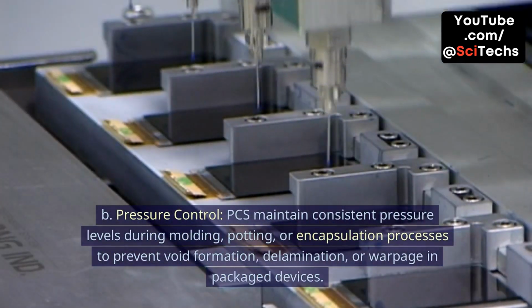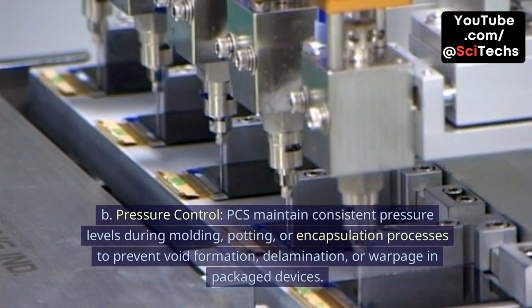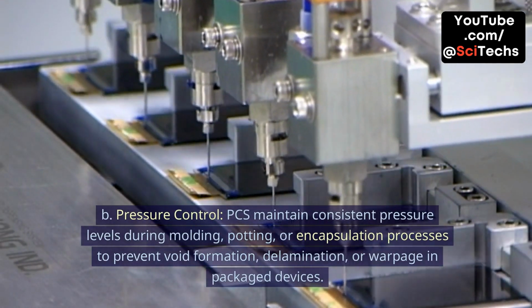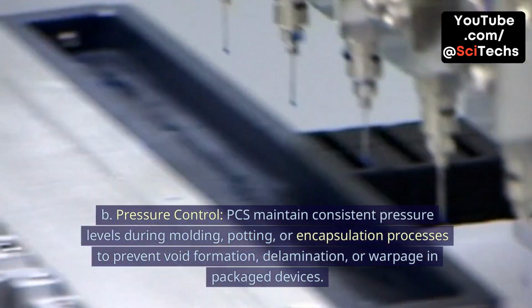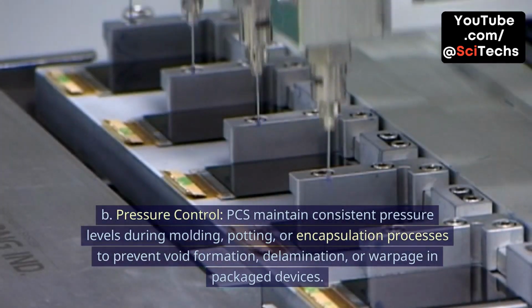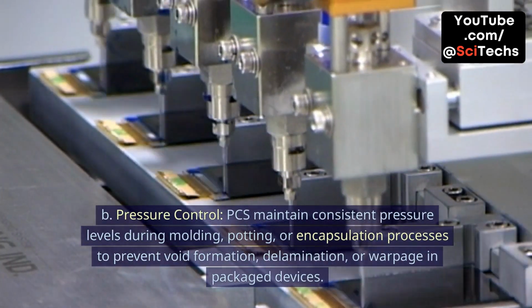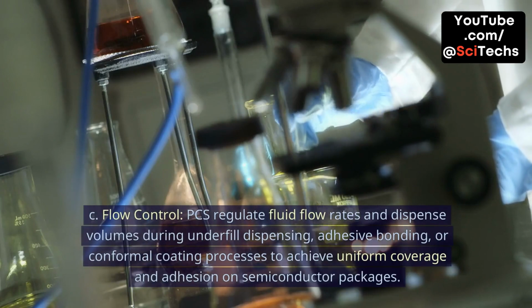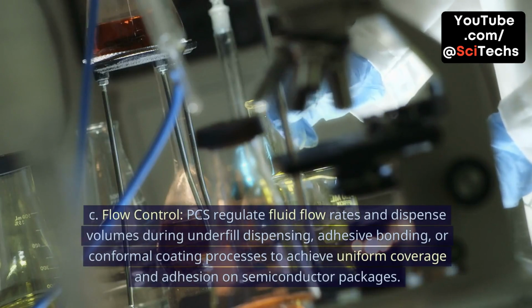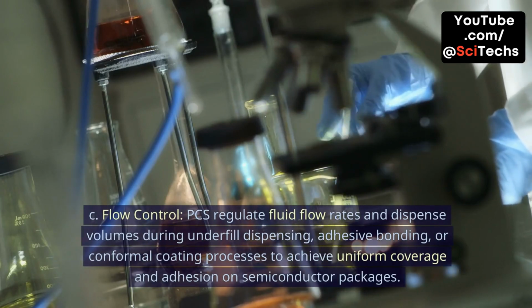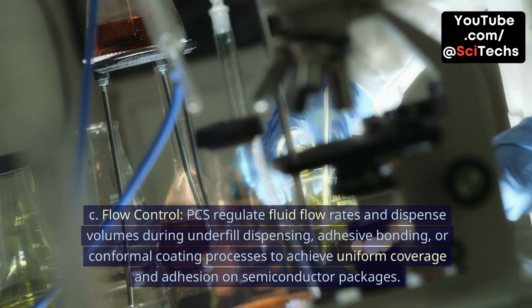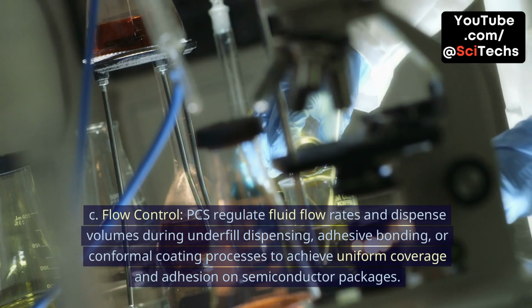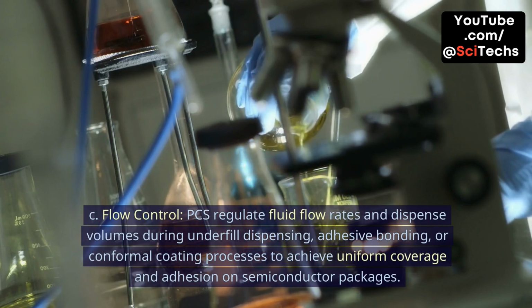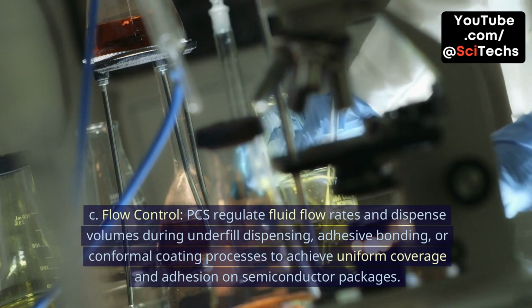B. Pressure control. PCs maintain consistent pressure levels during molding, potting, or encapsulation processes to prevent void formation, delamination, or warpage in packaged devices. C. Flow control. PCs regulate fluid flow rates and dispense volumes during underfill dispensing, adhesive bonding, or conformal coating processes to achieve uniform coverage and adhesion on semiconductor packages.